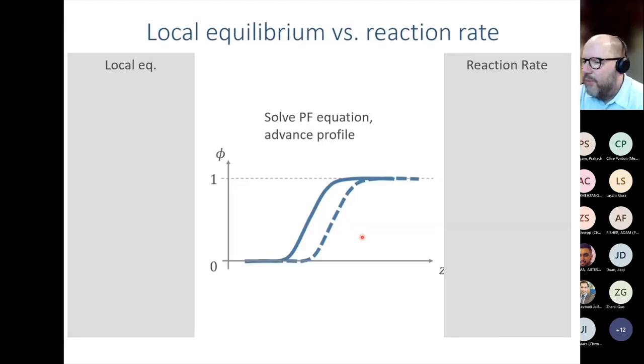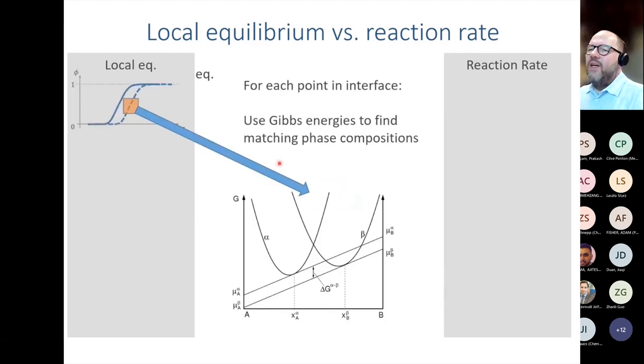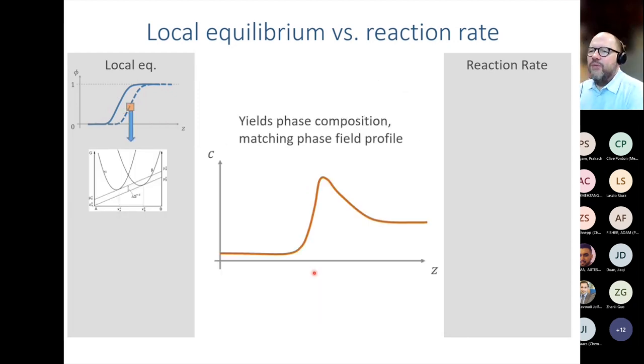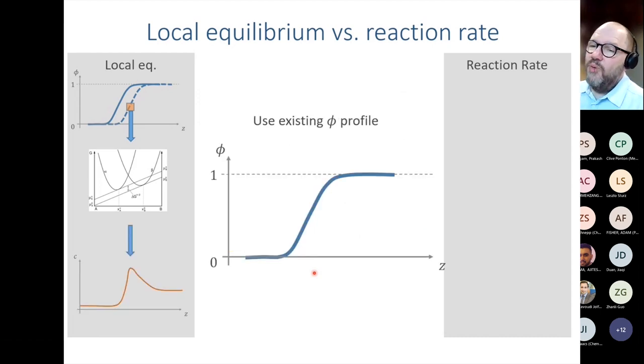So how would that work in the phase field context? In the classical way, when we do the local equilibrium, we have a phase field equation, and that would shift the phase field profile, representing a growth of a phase and a shrinking of another phase. For each point within that interface, we would then take the local conditions, the overall composition and the phase fraction, go into our Gibbs energy diagram, and from that, we would then also get the new phase compositions. Once we have the new phase compositions, we can then combine them and we get a concentration profile across the interface, which we can then use in a diffusion equation to simulate transport.